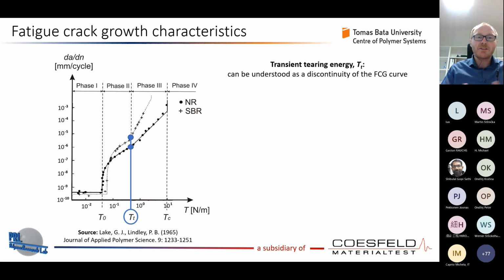Okay, let's go to the transient point. It is really important to understand each point within this fatigue crack growth characteristic. So the transient tearing energy, what is it, this point? Let's say it can be understood as a discontinuity of the fatigue crack growth curve. However, can in some natural way a discontinuity exist? That's a big question. And I never saw within a pristine rubber such a transient point in all I measured in the past.